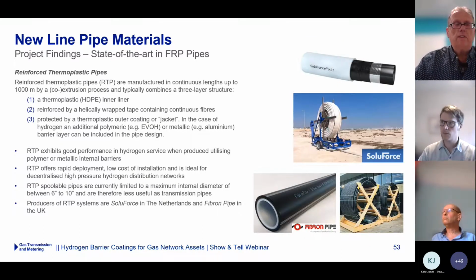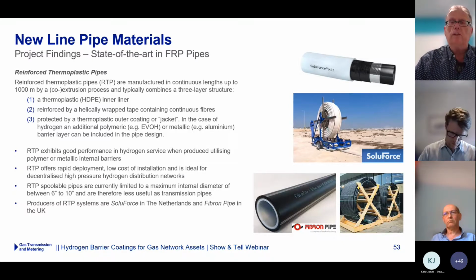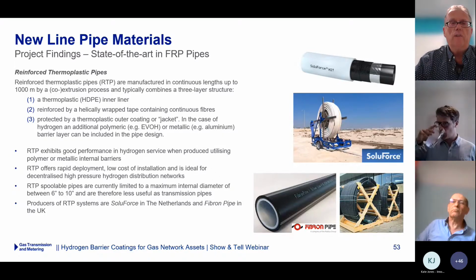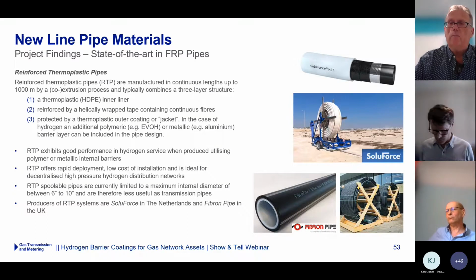So as an alternative, and there's quite a lot of movement in this area in the market, is the use of reinforced thermoplastic pipes. I think this is a very interesting technology because these pipes can be made in a continuous process. The process involves an extrusion, which is a continuous, relatively cheap process. In that case, it's a co-extrusion process, together with helical wrapping of a reinforced tape and a barrier layer, which can be, as in the picture on the top right, an aluminium foil or a thin layer of aluminium, but it can also be a polymer with much better barrier properties.